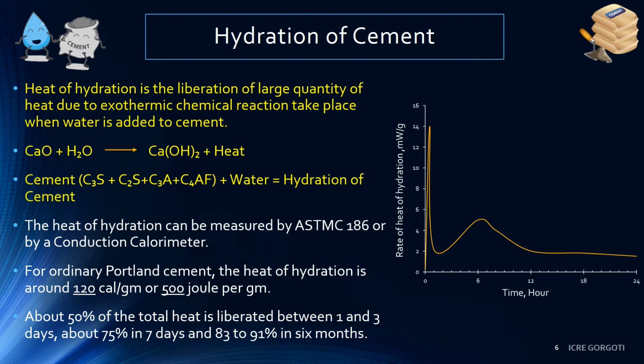Then, about 50% of total heat is liberated between 1 and 3 days, about 75% in 7 days, and 83 to 91% in 6 months.